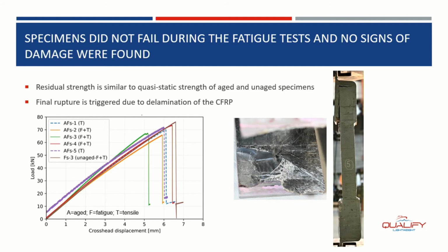So if you see a broken specimen at the right, that's because we did a residual tensile test at the end. There was no fatigue damage, not visible in the load signals, not visible from a visual point of view by inspection. So there was no damage at all. At the end, we did the residual tensile strength.